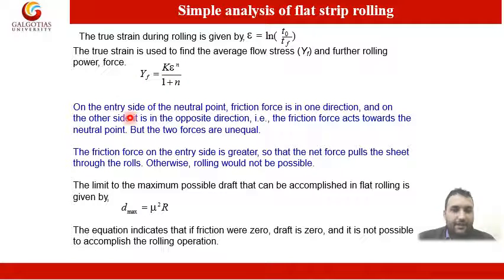On the entry side of the neutral point, the frictional force acts in one direction, and on the other side it acts in the opposite direction. That is, the friction forces act toward the neutral point. But the two forces are unequal. The friction force on the entry side is greater, so that the net forces pull the sheet through the rolls. Otherwise, the rolling